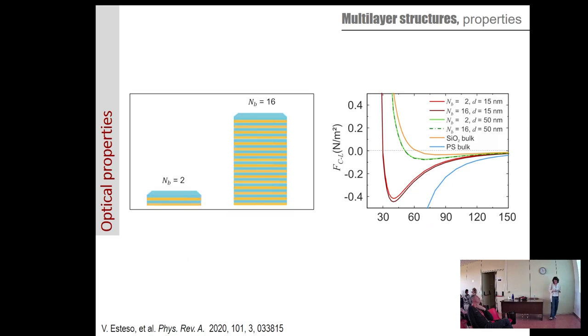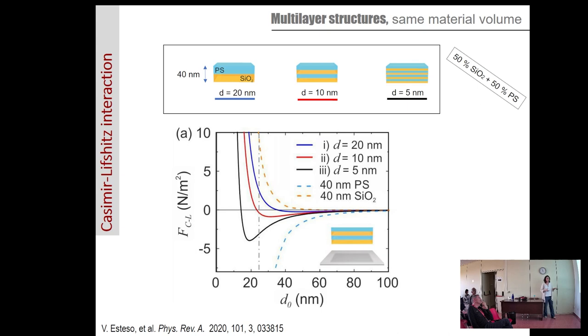So then we said, okay, we need to change the absorption properties of our materials, but we cannot consider anything like that because the more amount of material, the more absorbing material. So what we did was just to fix a total thickness of 40 nanometers made of silica and polystyrene in 50% each, and we arranged the material differently, which means that we are making the layers thinner. And with this, we really could tune the Casimir force as a function of the separation distance. Again, we have the same shape, and as you can see here, it is nice because with the same amount of material, but arranged differently, you can tune your system to have either a positive force, which is a repulsive force, you can cancel it, or you can have it negative, which is an attractive one. So by playing with the nanostructuration of the material, you can really manipulate the force.